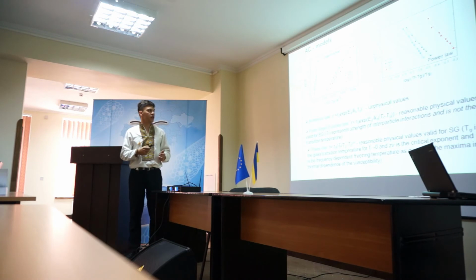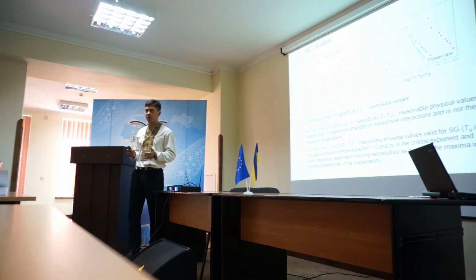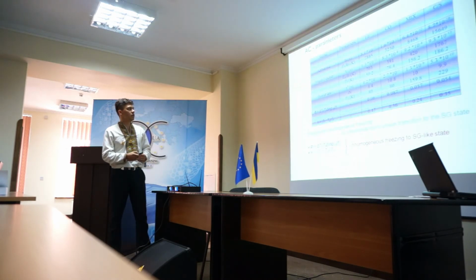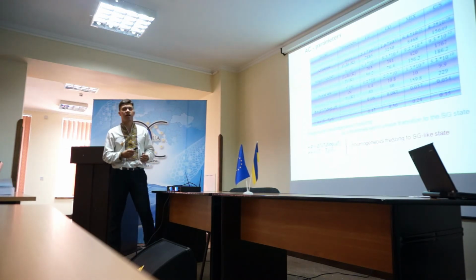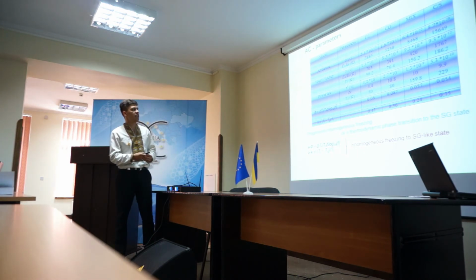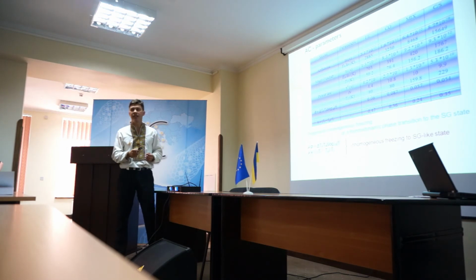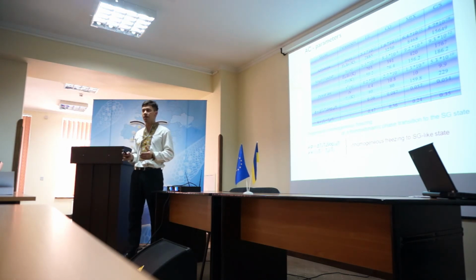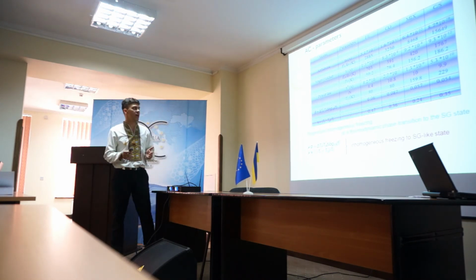The Arrhenius law is used for superparamagnetic nanoparticles. In this system, the interaction between nanoparticles is absent. And we obtain the next values. Tau zero is the characteristic relaxation time. This is the energy barrier. And we obtain physically unreasonably small and high values for the Arrhenius law for all samples. It means that in this system some dipole interactions are present, and it points to spin glass behavior.